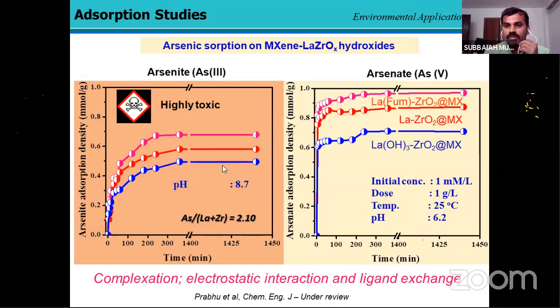Also, we had already developed the lanthanum fumaric MOF moiety. From the MOF, we developed lanthanum oxides. Then we combined it with a zirconia moiety and intercalated it on the MXene phase. Then we showed higher efficiency than the reported lanthanum-based materials until now. Also, the interesting phenomenon was that the lanthanum zirconia-based material showed almost 80 milligram per gram of adsorption